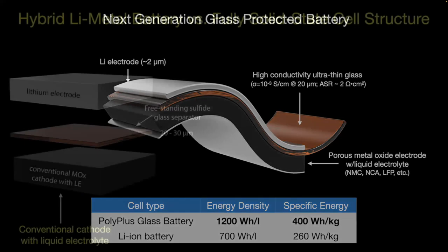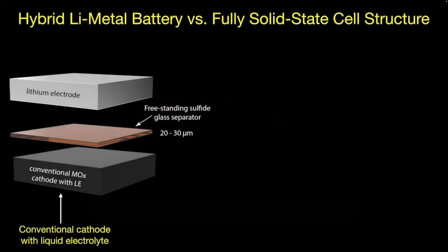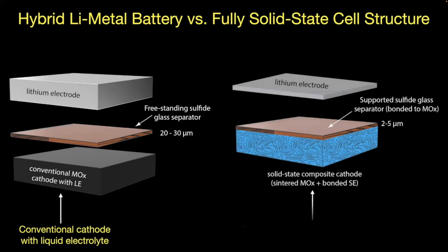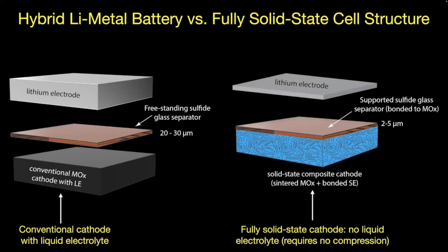We also have another approach, which is happening now within Polyplus, which is a fully solid state, zero liquid cell, which requires a solid state cathode. Of course the glass is solid state, lithium itself is solid state, but that means transitioning to a completely solid cathode. So that work is happening now. We are building basically a three-dimensional cathode which will have sulfide solid electrolyte interspersed within that structure. Again, we don't expect to need any pressure to hold this together.